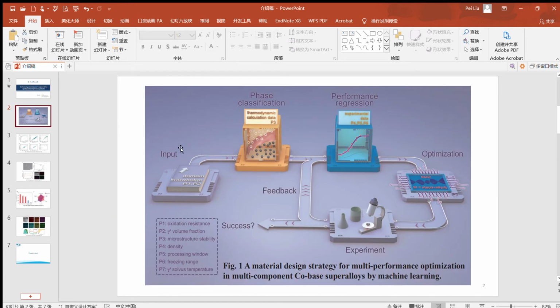In this figure, 7 properties in gamma-prime strengthened Co-based superalloys, such as the microstructural stability, gamma-prime solvus temperature, gamma-prime volume fraction, density, processing window, freezing range, and oxidation resistance were simultaneously optimized. A machine learning framework flow consisting of screen filters, global optimization algorithms, and experiment feedback is used to select the potential candidates with desired properties for experiment and characterization.